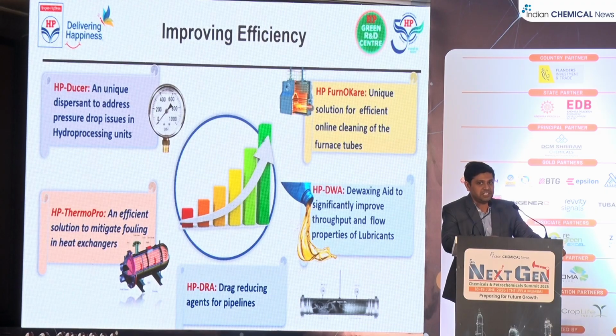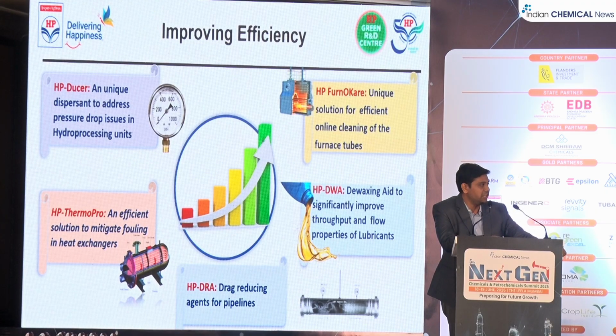Then comes our efficiency-improving additives. Here we have a couple of additives. HP-Ducer is an additive where we have seen that due to contaminants in the crude, especially inorganics and metals, they get deposited over the fixed bed catalyst of the hydrotreater unit or naphtha hydrotreater unit. Because of that, we get very high delta P, so you need to run your unit at a lesser feed rate to match the design delta P. By using this chemical periodically, after 7 to 10 days, you can control the delta P within the unit so that more feed can be processed.